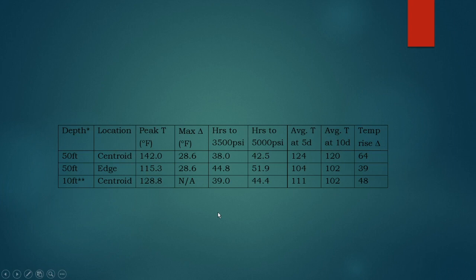We also were able to, because of maturity, evaluate the strength of this concrete as it's curing, and it took a certain number of hours to reach, for example, 3,500 psi, and then 5,000 psi. And those are important numbers because what we don't want to have happen is one area of the concrete much higher in strength than another area of the concrete, because that can also cause some stresses. And it was pretty interesting that we had a peak of 142 degrees, but then by day 5 it had dropped down to 124. And then by day 10 it had only dropped another 4 degrees. So this concrete was hydrating slowly, and it was doing exactly what it was supposed to be doing.